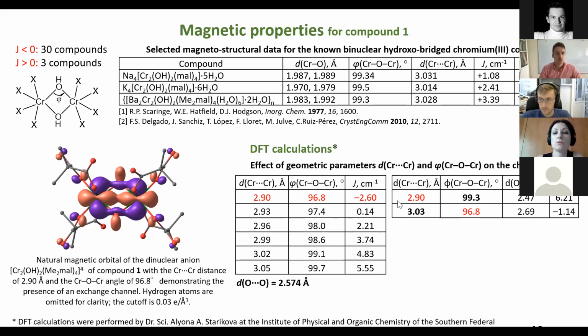When the metal-metal distance was fixed at 2.9 angstroms and the angle was kept equal to 99.3, like in structure 1, the value of J was positive. When the chromium-oxygen-chromium angle was fixed at the value of 96.8 degrees and the chromium distance was kept equal to 3.03 angstroms, like in our complex, the calculated exchange constant was indicative of weak antiferromagnetic exchange. Therefore, it can be concluded that the chromium-oxygen-chromium angle rather than the chromium distance has a greater effect on the character of the exchange interaction in compound 1.